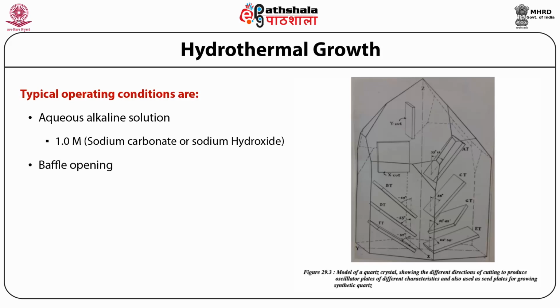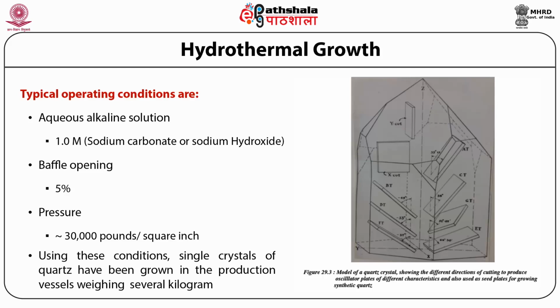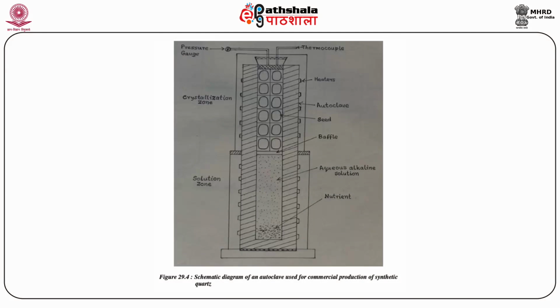Baffle opening is kept at 5%, and the pressure is maintained approximately of the order of 30,000 pounds per square inch. Using these conditions, single crystals of quartz have been grown in the production vessels weighing several kilograms. Figure 29.4 is a schematic diagram of an autoclave which is used for commercial production of synthetic quartz.